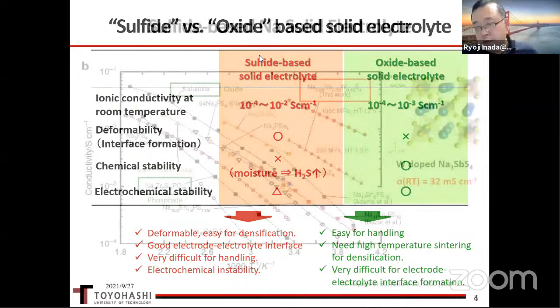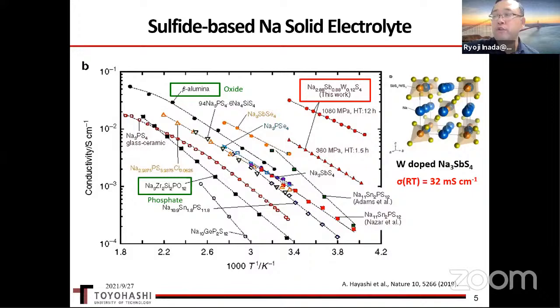On the other hand, since 2010, many kinds of sulfide-based sodium solid electrolytes with a conductivity well above 1 millisiemens per centimeter have been reported, as shown in this graph, at room temperature range. Among them, the tungsten-doped sodium thioantimonate, with this composition and a cubic crystal structure, shows very high ionic conductivity above 30 millisiemens per centimeter at room temperature. This is well above current liquid electrolytes for sodium-ion batteries, I think.